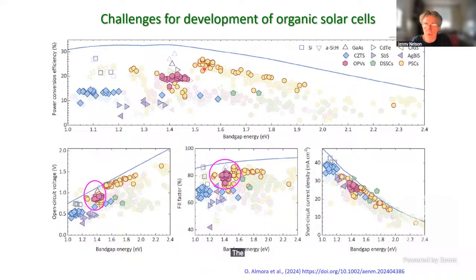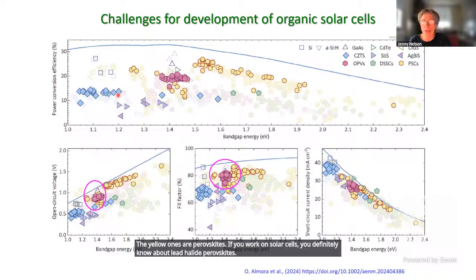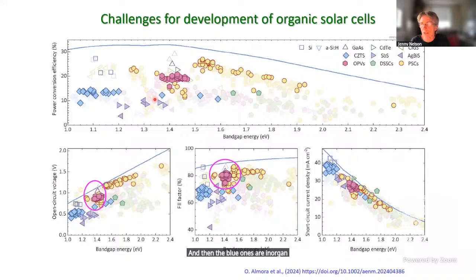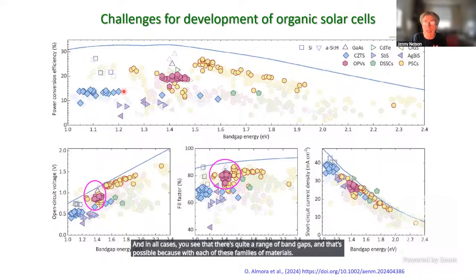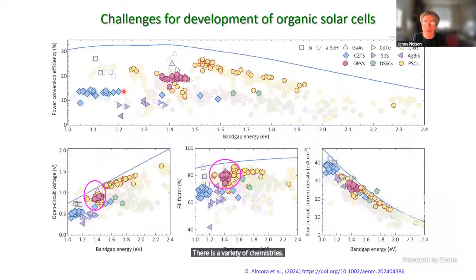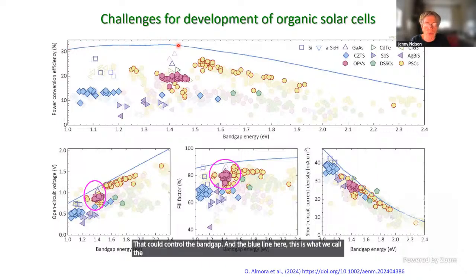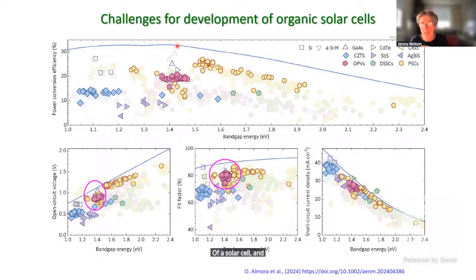The yellow ones are perovskites. If you work on solar cells, you definitely know about lead halide perovskites. And then the blue ones are compound inorganic semiconductors like kesterites. And in all cases, you see that there's quite a range of band gaps, and that's possible because with each of these families of materials, there is a variety of chemistries, a variety of different components that could control the band gap. And the blue line here, this is what we call the Shockley-Queisser limit to efficiency. So it's a kind of thermodynamic limit to the efficiency of a solar cell. And so nothing is at the limit.